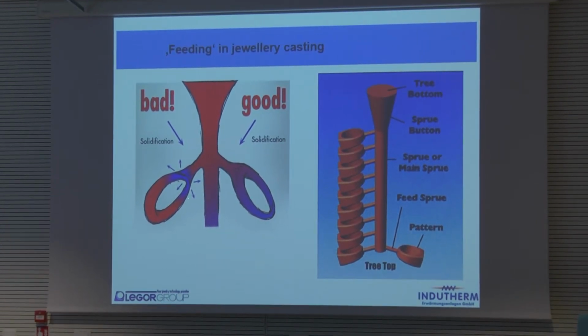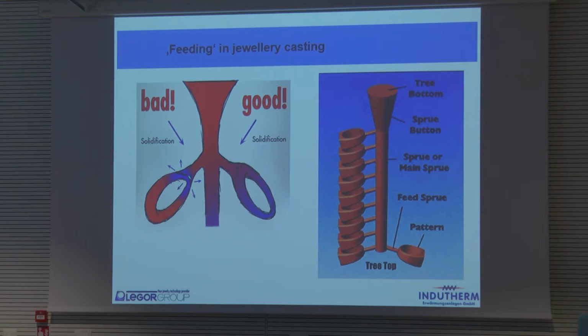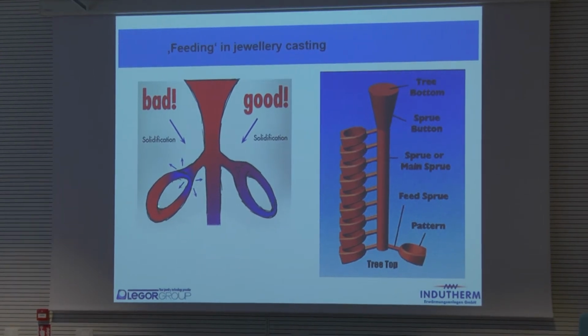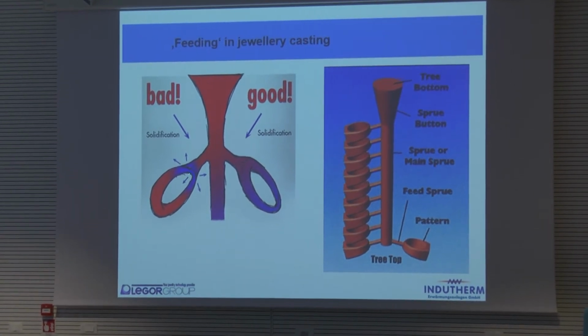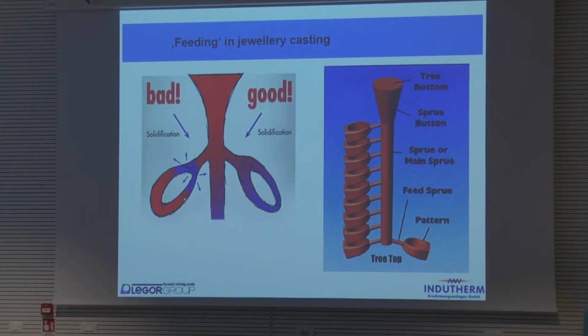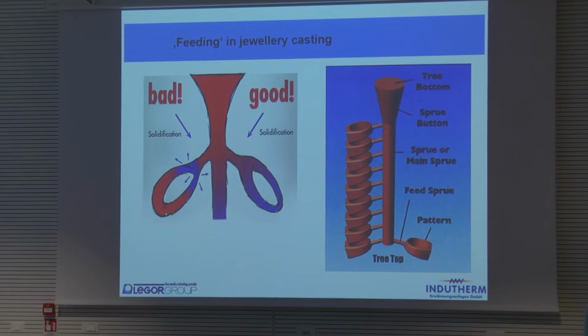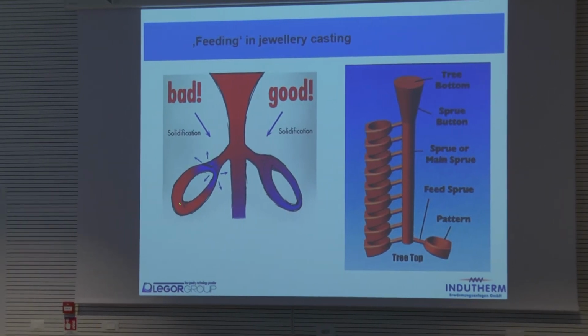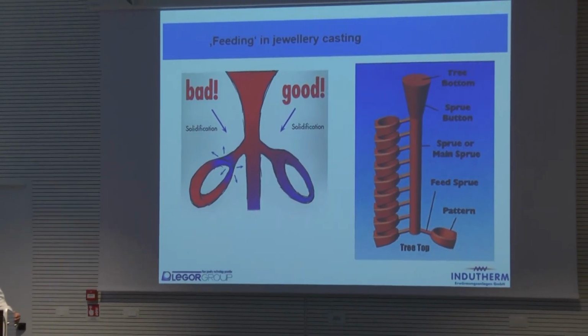Here's just a very generic example. We have a ring and we have a heavy part of the ring here. We put the sprue on the opposite side, and this asks for problems. So this part of the casting may solidify first before the rest of the casting. So when this is solidified, no molten metal can be fed into the other part of the casting. So this will ask for shrinkage porosity in this part of the ring.